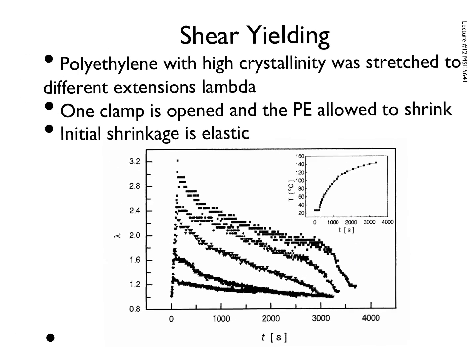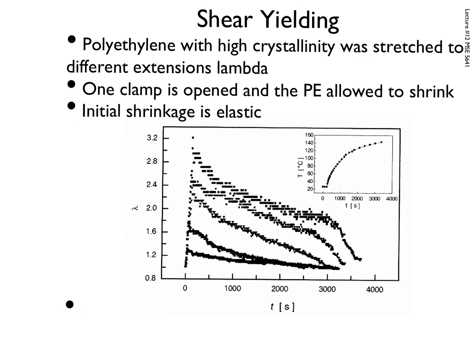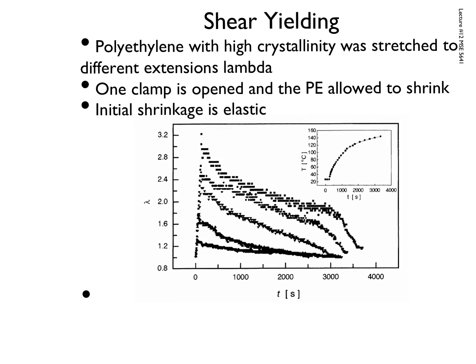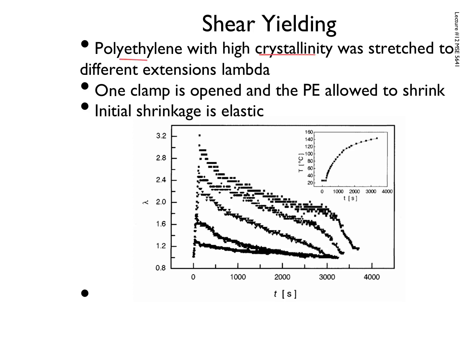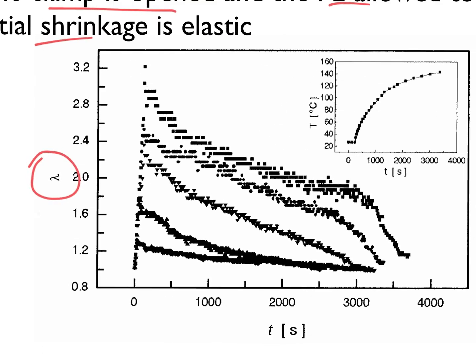All right, and so this is an example of that, in which we take polyethylene with a high crystallinity, so clock diagram, stretched to different extensions lambda. Again, we're talking about this lambda, in this case it's on the vertical axis. And then what happens is they actually open the clamp and they allow it to shrink, and they look at that initial shrinkage. And so what you're doing is you're taking polyethylene, straining it, and then you open the clamp and you go through this thermal cycle.